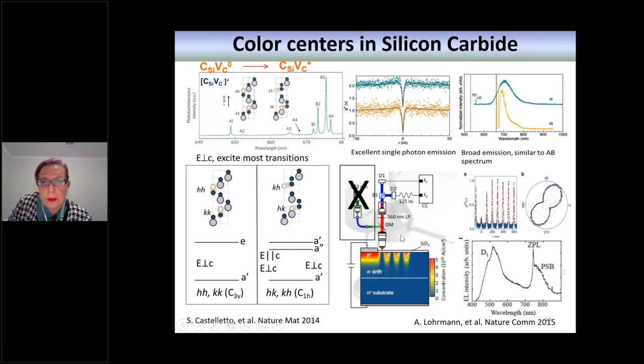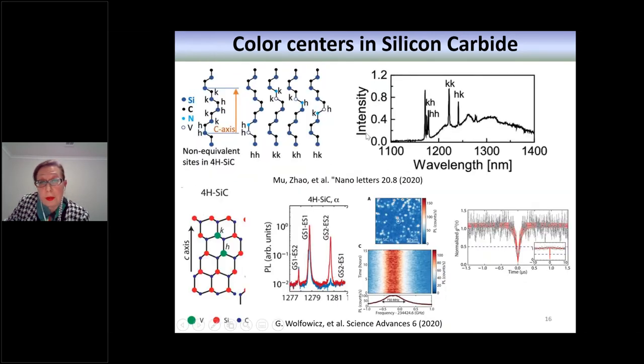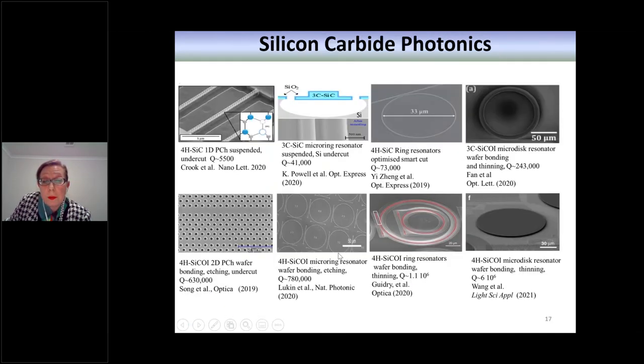The brightest single photons at room temperature are in the visible and are attributed to the carbon antisite-vacancy pair. Other emitters are potentially not yet fully understood, but are at the interface with the silicon oxide and can be controlled and excited also electrically, and they are quite bright. Then recently work has been done also on the NV center in silicon carbide and vanadium, for which the study from the spin point of view is limited. Anyway, they are still operating. The NV center operates at room temperature.